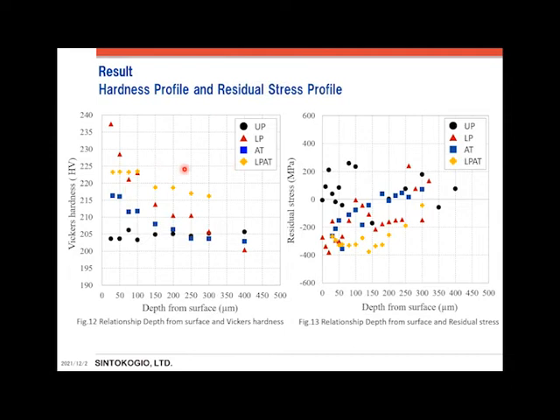This page shows the result of hardness measurement and the residual stress measurement. In both figures, black circle mark is UP, red triangle mark is LP, blue square mark is AT, and the orange diamond shape mark is LPAT. The left figure shows the relationship between Vickers hardness and the depth from surface. The surface hardness of LP and LPAT increased compared to UP. The LP condition shows the most improvement in hardness, rising to 238 HV.